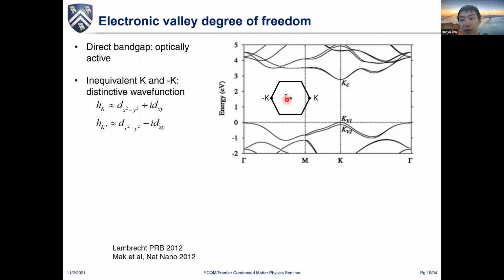And then, because these materials have inversion asymmetry, there are two valleys located at different momentum space. If electrons and holes scatter from one valley to the other, they have the same energy, so they can scatter, but this scattering will be associated with a valley phonon with non-zero momentum, or in our case, it would be chiral phonons.